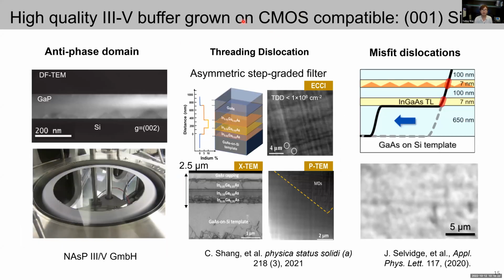Well, the first strategy is still to try to reduce the defects in the semiconductor material itself, in addition to threading dislocations, but also antiphase domains and misfit dislocations. So to deal with antiphase domains, people finally found that a thin layer of gallium phosphide buffer can efficiently suppress its effects. And nowadays, 12-inch gallium phosphide on silicon wafers are commercially available with no antiphase domains. And to deal with the threading dislocation density, people can still make it even smaller. So this is the most advanced asymmetric step-graded filter.